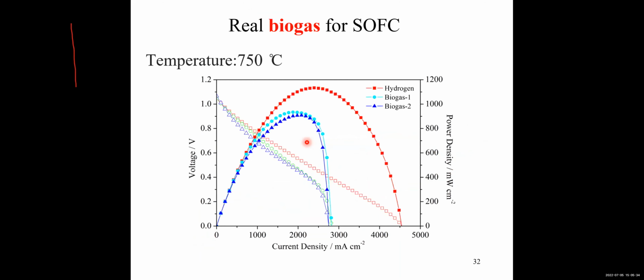We tested our SOFC using biogas and found the performance is not bad. Of course, compared with hydrogen fuel, the power density is not as high, but it's still very good. Using hydrogen as a fuel, we can achieve a power density of around 1,100 milliwatts per centimeter squared, but using real biogas, we can still achieve about 900 milliwatts per centimeter squared peak power density. So this is pretty good.